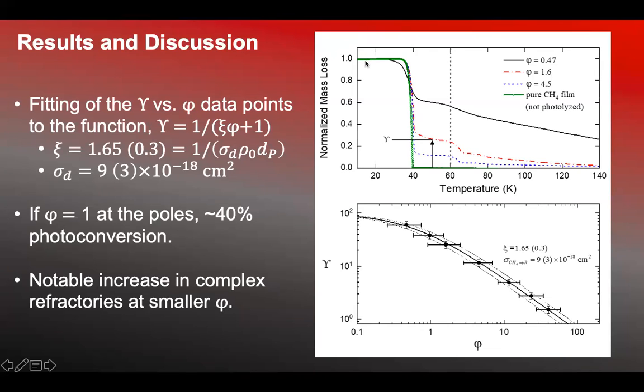So when you melt the ice, when you bring the temperature up, if it's a pure methane film, it just goes straight from total mass present to nothing. But if this has been photolyzed, if there are these photolysis products there, you get these kind of bends and knees in the profile. And so that implies that there are these photolysis products there. And we actually measure the amount of the photolysis product based off of these curves, and we correspond that to the incident flux that we used in each of these experiments to obtain that phi value.